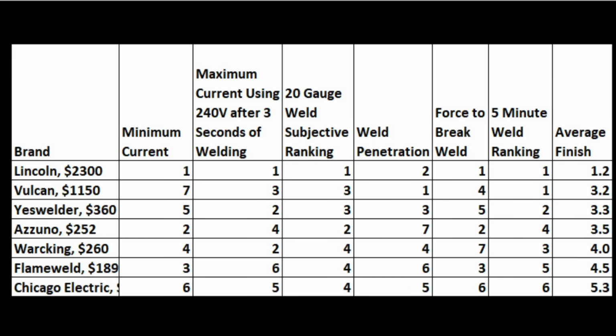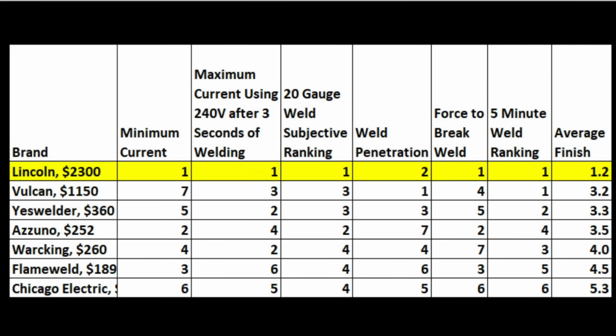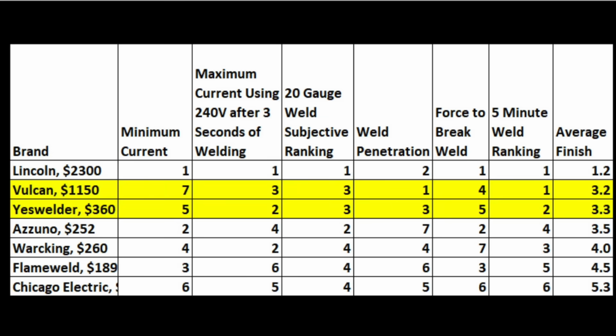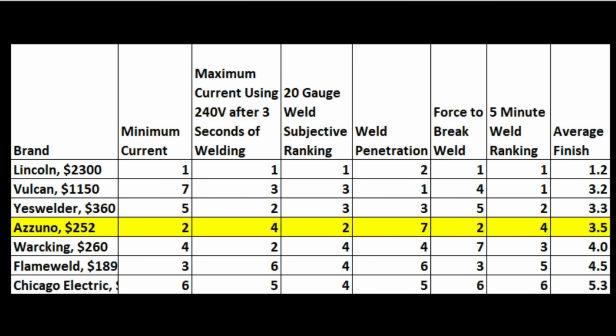So which welder is the best? The Lincoln finished first in every category except for weld penetration. However, the Vulcan and Yeswelder are both very competitive with each other, with the Vulcan barely finishing ahead of the Yeswelder. If you're really concerned about the budget, the Yeswelder is a great buy at about $360. If it's all about value, the Azzuno is very hard to beat at around $250, and there's a good chance you could find a coupon to bring the price down even more.